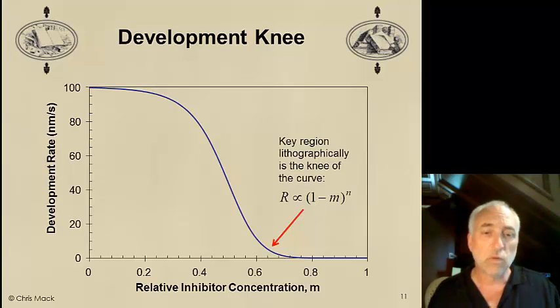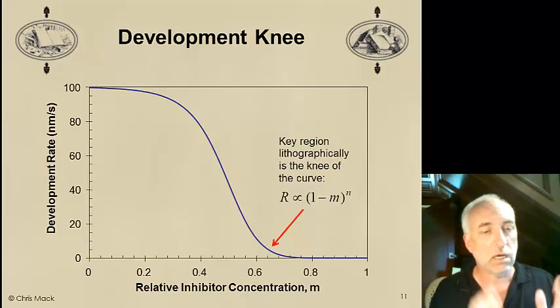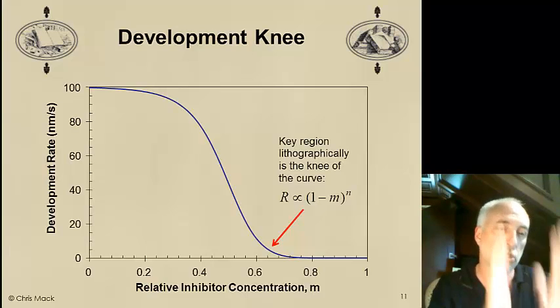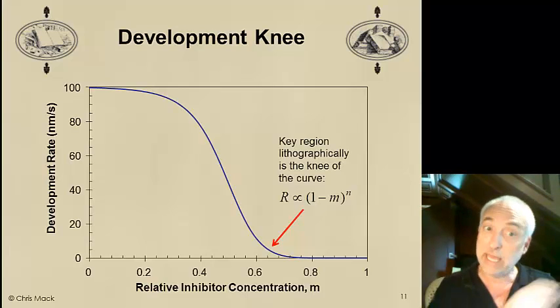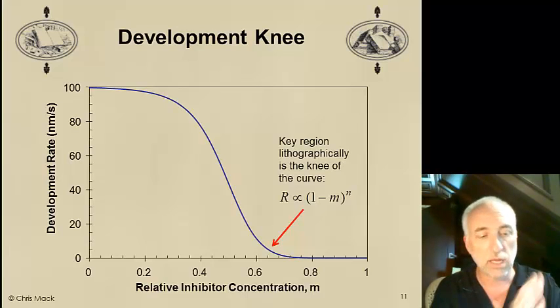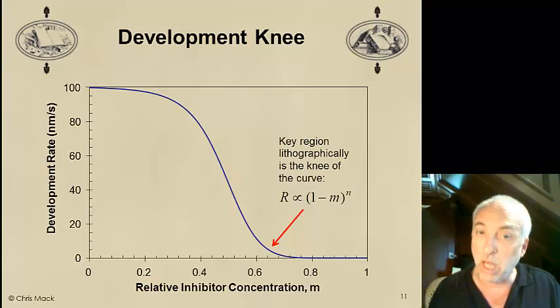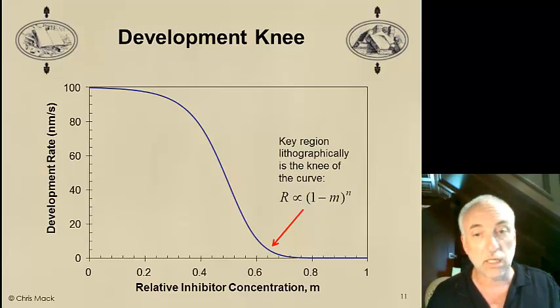when I'm done developing, at the edge of the photoresist profile when I'm done. When I'm done, I'm going to make a feature, a resist line that has reasonably vertical edges. And the region on one side is going to be highly soluble and all the resist will dissolve away. But right at that edge, the development rate must be pretty darn low, or else the resist wouldn't remain.